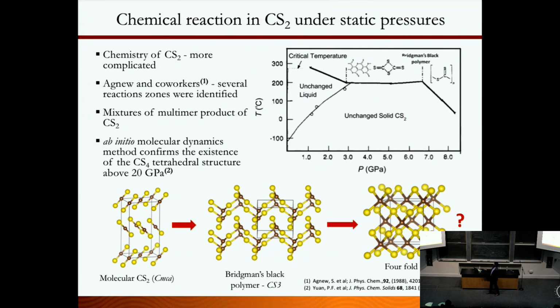If I give a little bit of background, this material has been studied extensively many years ago. This is one of the first samples studied by Bridgman, who got the Nobel Prize for high pressure experiments in 1946. He discovered this sample called Bridgman black, which has threefold coordinated carbon and sulfur atoms. You have linear CS2 molecules, but when you pressurize to higher pressures, it transforms into this polymer. And if you subject it to more pressure, it can go to CS4, the fourfold coordinated carbon disulfide. So this is roughly the phase diagram people have studied, going into an energetic material and also increasing the coordination from twofold to fourfold.